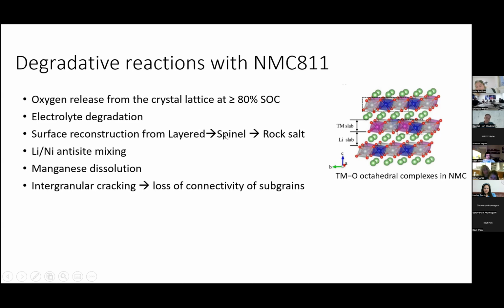Lithium plus and nickel 3 plus exist with almost similar radius. Because of this, lithium gets diffused to nickel, or nickel gets diffused into the channels of lithium. And there is manganese dissolution. When we charge and discharge for a longer period of time, there is overall structural loss of the material, which is seen as intergranular cracking, which will lead to higher electric resistance in the cathode material.